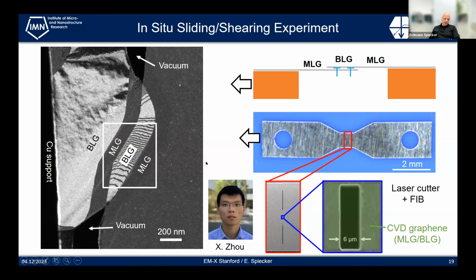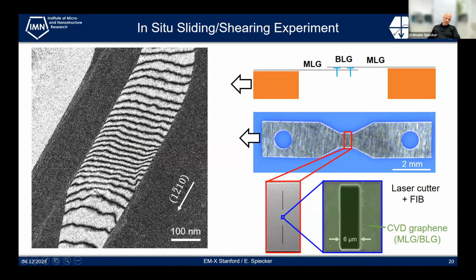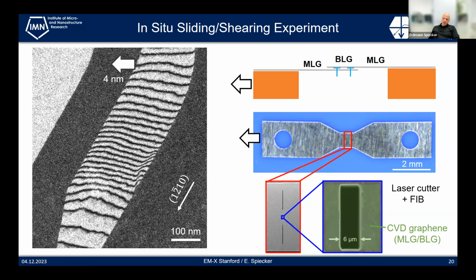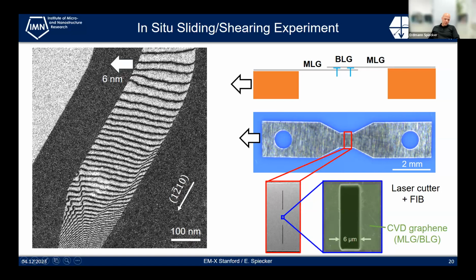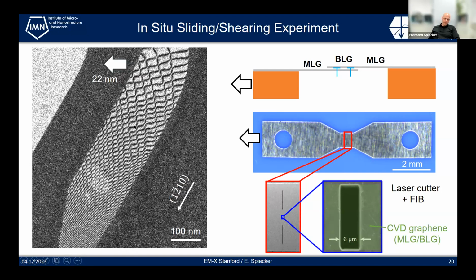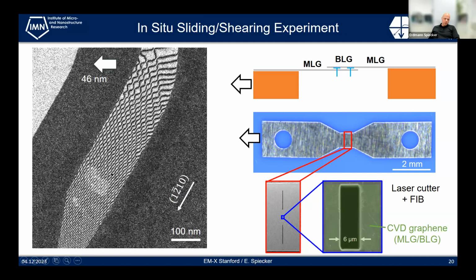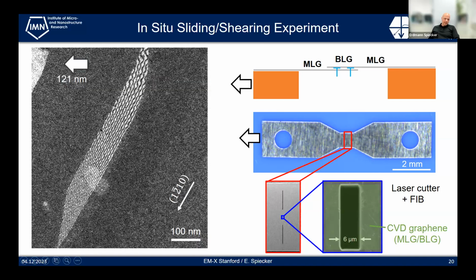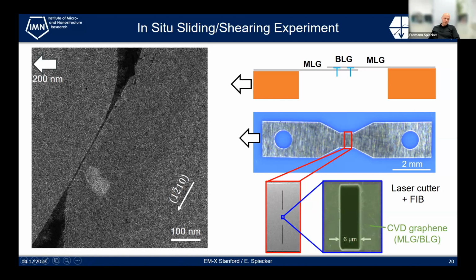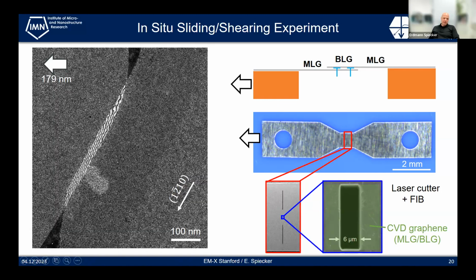And if we look a little bit more carefully, we see already that there are dislocations, so lines. This is a dark field image formed with a 1-1-0 reflection, and you nicely see these dislocations at the interface of the bilayer graphene. If we now pull on this dog bone sample, we see that new dislocations evolve here from the bottom part and move up, and you get a network of dislocations which becomes more and more dense the more we pull. And of course the overlapping region is reduced, and finally the two monolayer flakes are separated from each other. So let me go back.